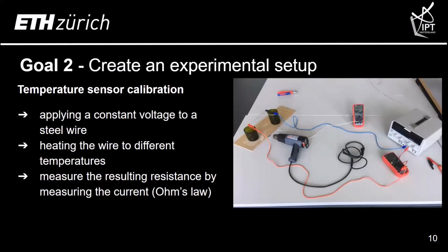Now we come into the experimental verification of the theoretical model. For that, I first had to build myself a good temperature sensor, which I could place on the bottle to measure the temperature in a good way. For that, I calibrated a steel wire where I measured the resistance and heated it up to certain temperatures, thus giving me a function for the temperature of the resistance.